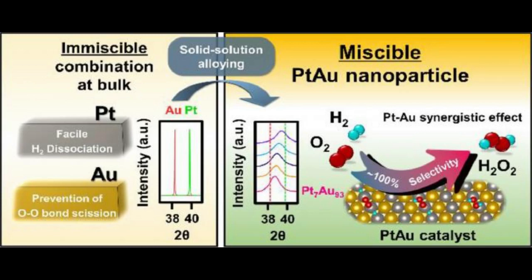The joint research team between KIST and Korea University developed a new type of platinum-gold alloyed nanoparticle catalyst. Although it is difficult to homogeneously mix platinum and gold due to the intrinsic immiscibility of the metals, the researchers successfully synthesized nanoparticles in alloy form by forcibly reducing precursors of platinum and gold. Using this method, the content of each metal in the particle could be controlled by adjusting the amount of precursors.